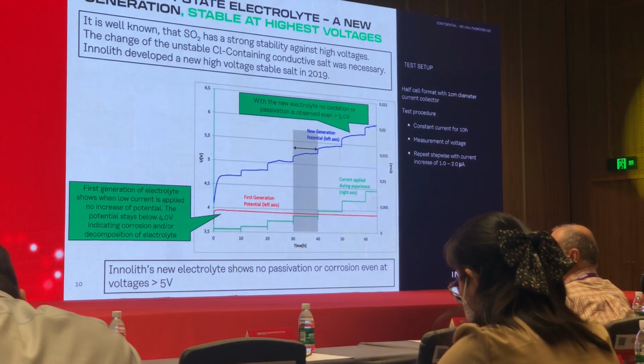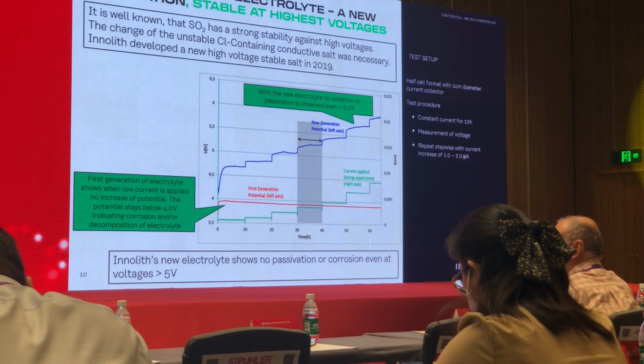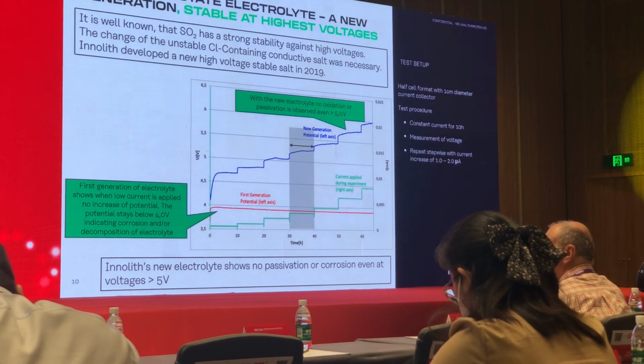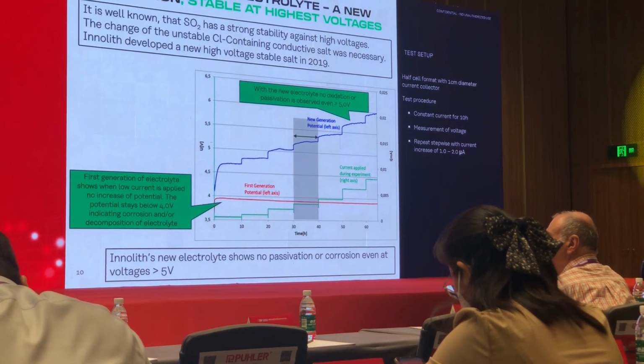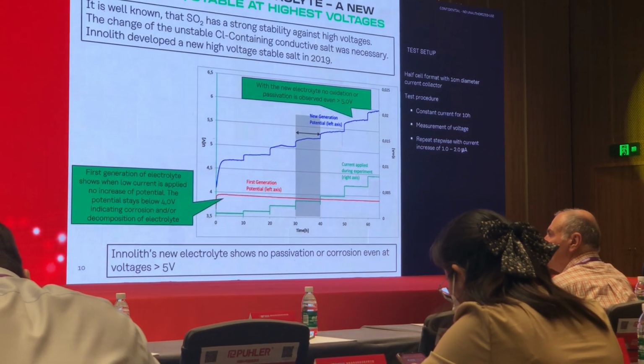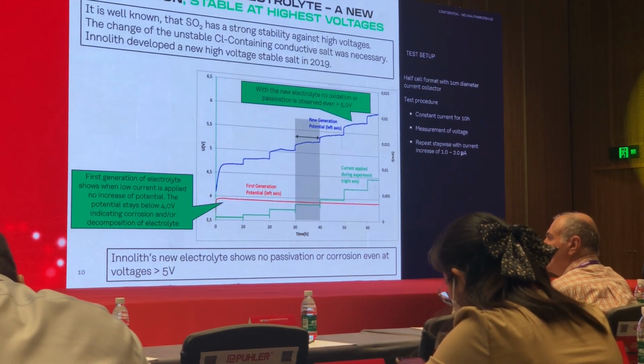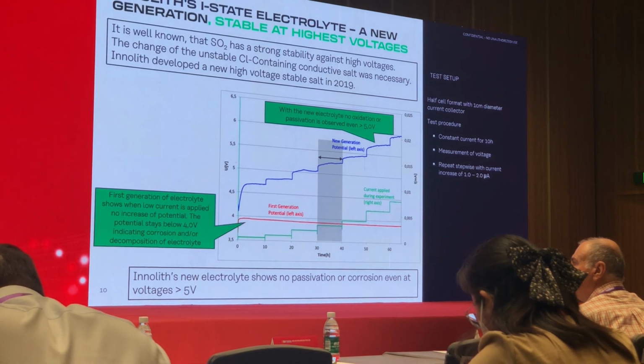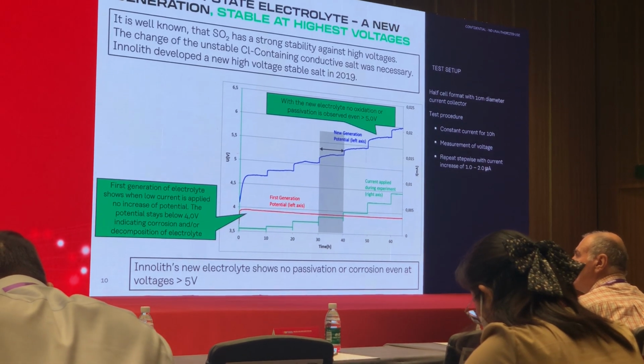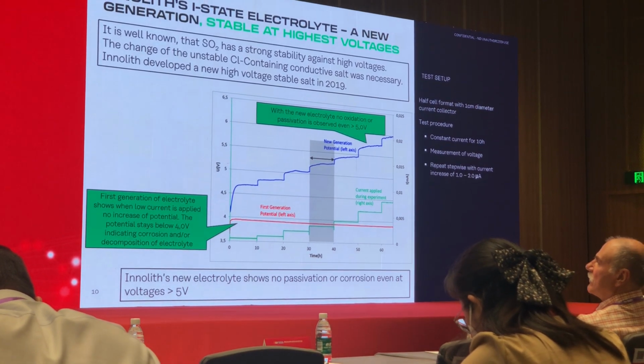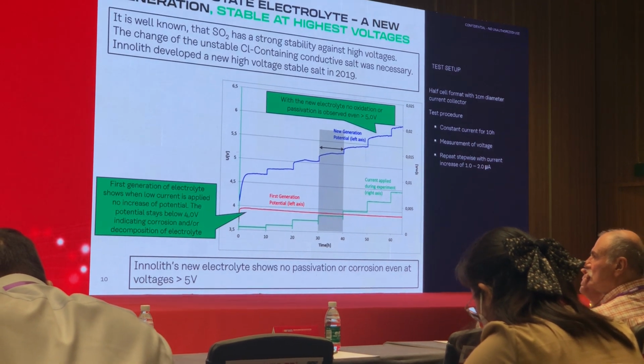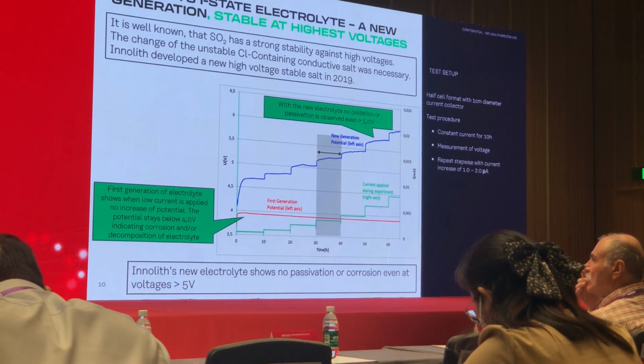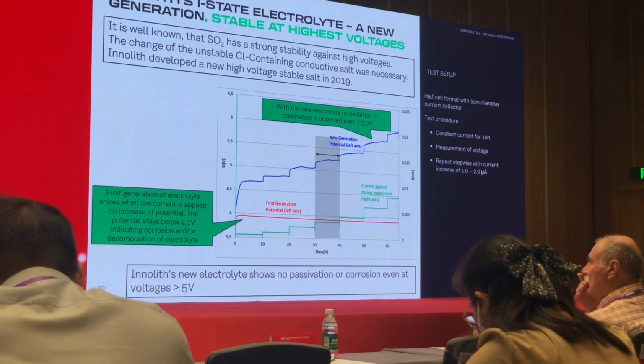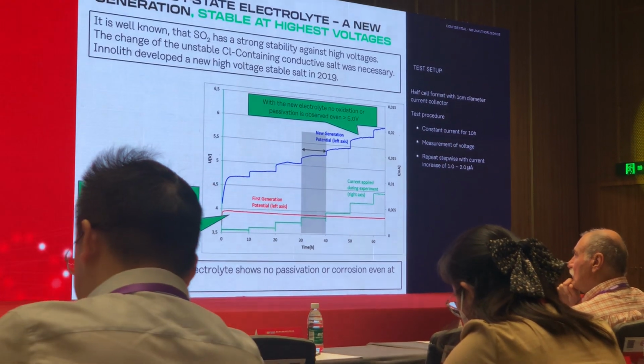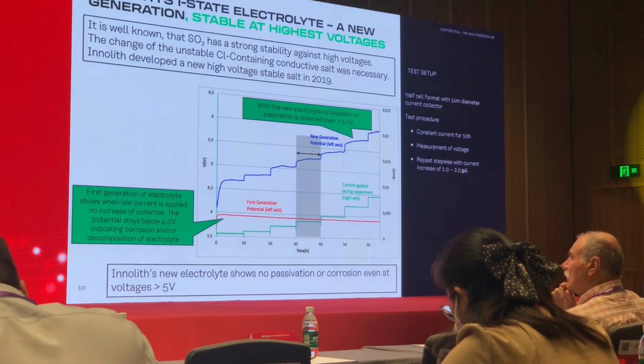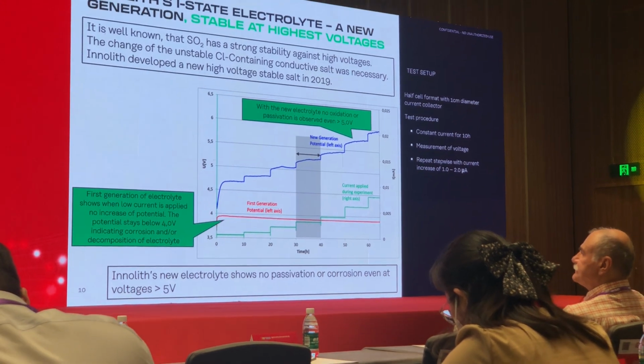And what you can see here is a corrosion test we have done in order to discard the different formulations. And in red, you see our first generation. A current is applied on an aluminum current collector, and the potential is analyzed. And so you see that with the first generation, below 4 volts, a constant potential without changing, meaning that oxidation of electrolyte happens.